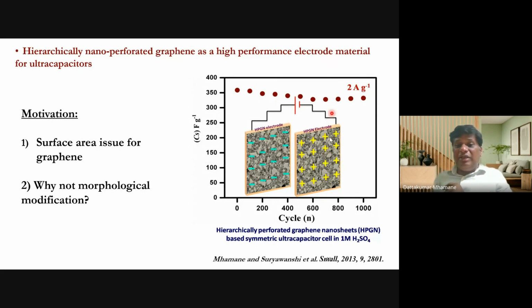This is the device we made by using perforated graphene, nano perforated graphene, and the perforation size was uncontrolled. You can see 10 nanometer, you can see 50 nanometer, you can see 2 nanometer, you can see 10 nanometer. So why are these holes of different size? That question was asked at that time. We concluded that oxygen containing functionalities are present which are of different size, and because of that the holes produced are also of different size, and that is why we named it hierarchically nano perforated graphene, a good conducting, high performance electrode material for ultracapacitor or supercapacitor.